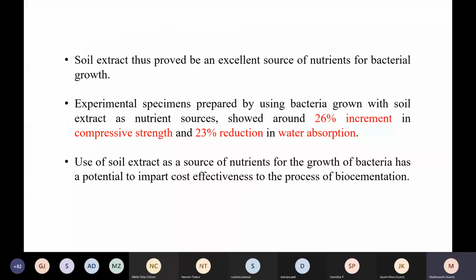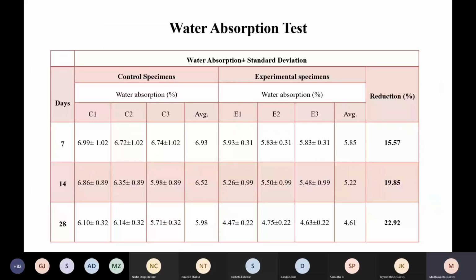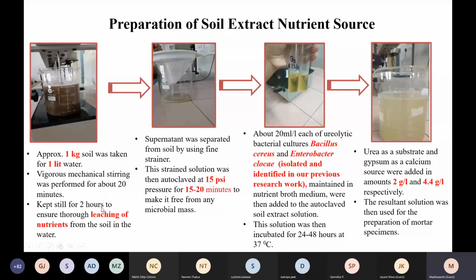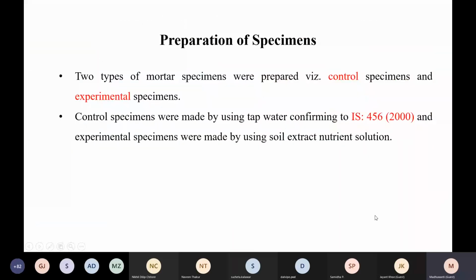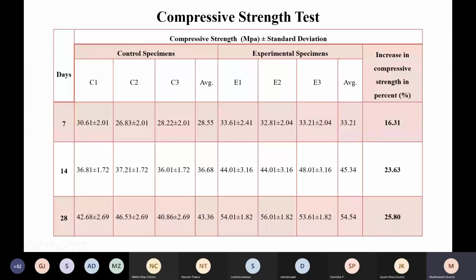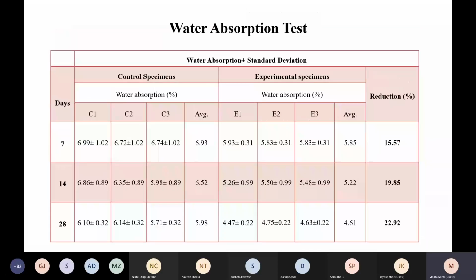So now, I'll just go back to the previous slide, that we have used this leached out nutrients which are there in the supernatant to grow these two types of urease active bacteria. Incubation was done, optical density was checked, and then we were confirmed that bacteria were grown profusely. Then urea substrate and gypsum calcium source were added, and then this biocementing solution was used to cast the experimental specimens, and the results are in front of you.